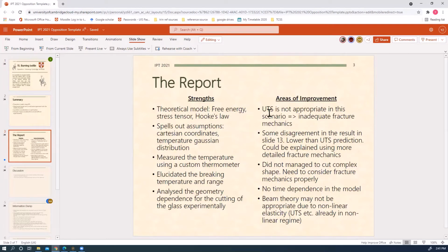Mm-hmm. Or we could potentially go to the other extreme, which is to control the surface cracks. For example, we can sand the surface to create deliberate micro cracks and make it consistent across the runs to improve the repeatability of the data. This also leads to a point related to the cutting of complex shapes. As we have discussed, surface fracture plays a very important role, and with the existence of a surface fracture, the fracture tip can propagate very easily. So if we can guide this surface fracture by making indentations on the surface of the glass, it might help you to cut complex shapes.